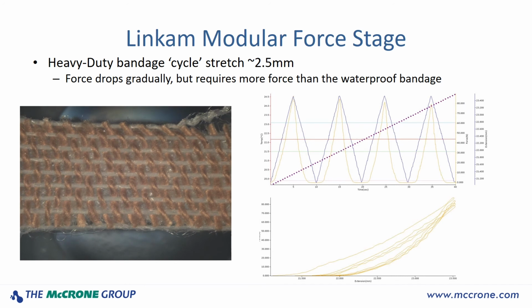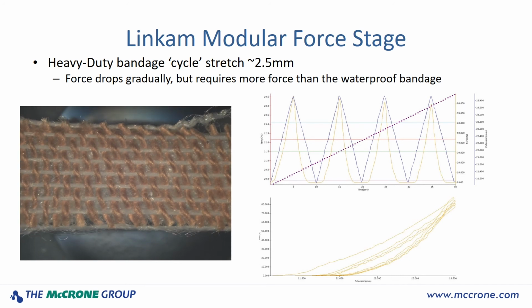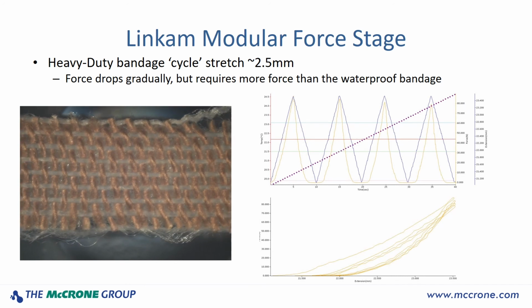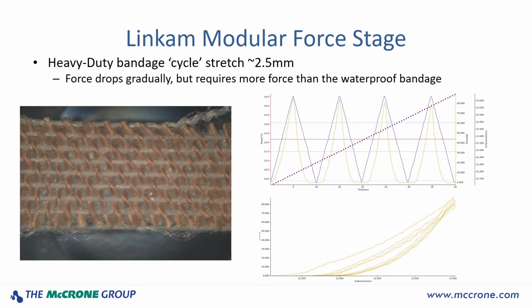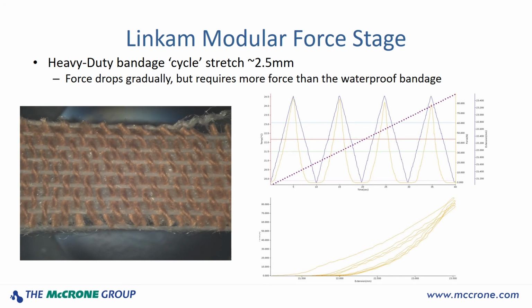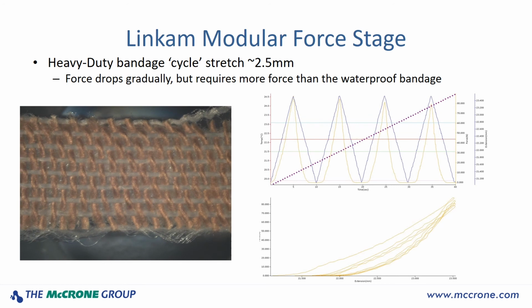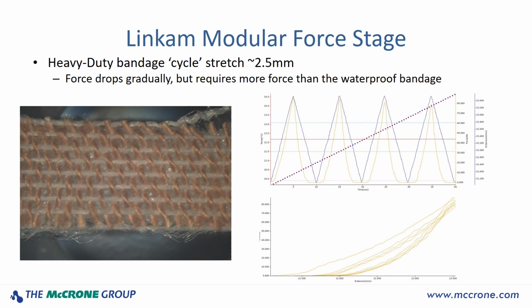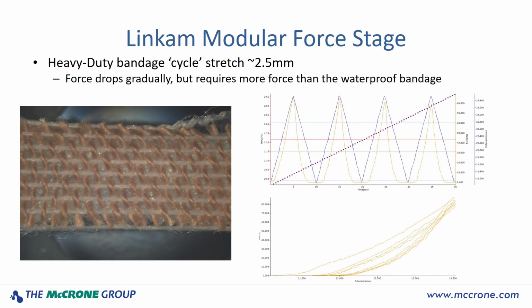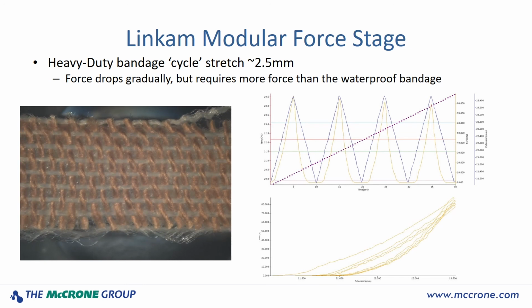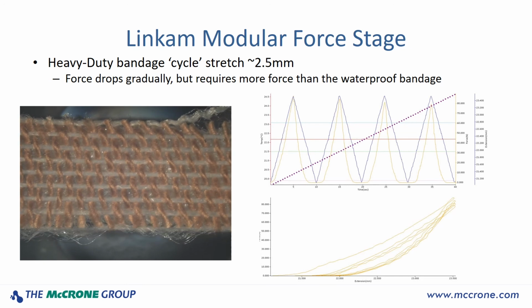The first test for the heavy-duty bandage was the same 2.5 millimeter cycle that we did for the waterproof bandage, and we saw similar results. The force dropped gradually as cycles went on, but it seemed that the woven pattern of this bandage allowed for more elasticity and it maintained its force better than the waterproof bandage.